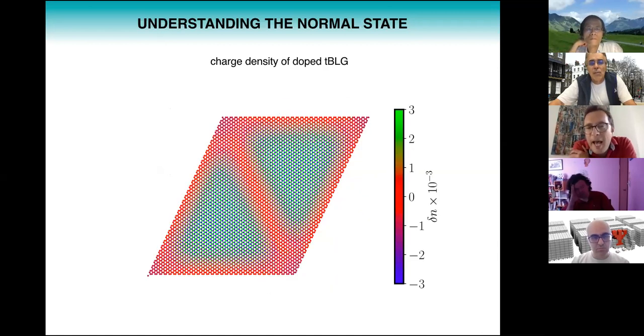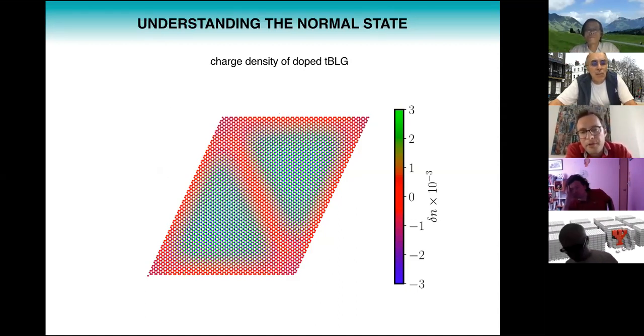So why does this happen? If you just have tight binding, then of course you cannot capture the effect of doping on the band structure. So Hartree theory gives you this qualitatively new effect. The reason is that microscopically, we're dealing with an inhomogeneous material. Here I'm showing you the charge density of doped twisted bilayer graphene, where I've added 3 electrons in the moiré cell.